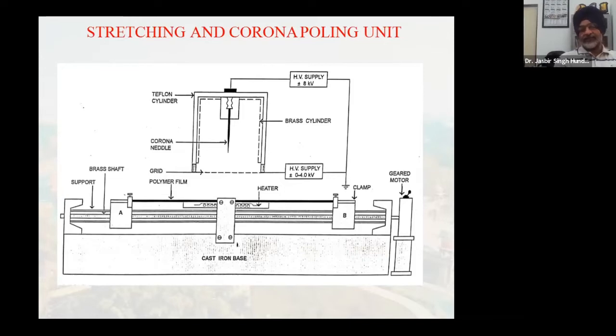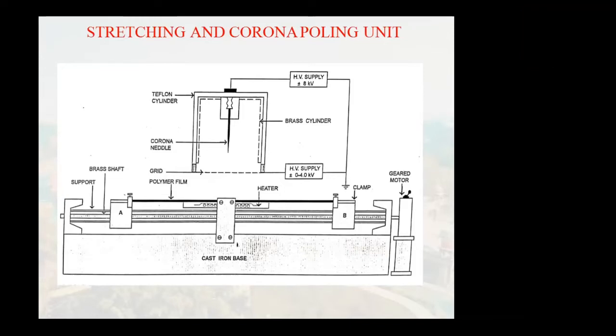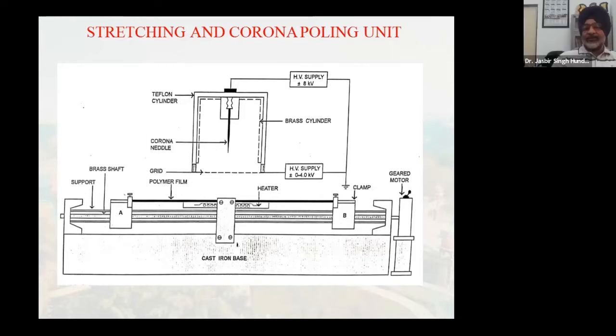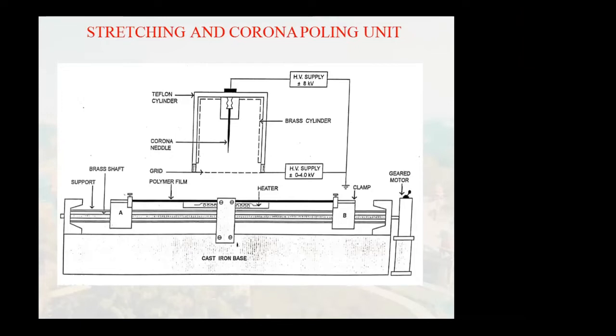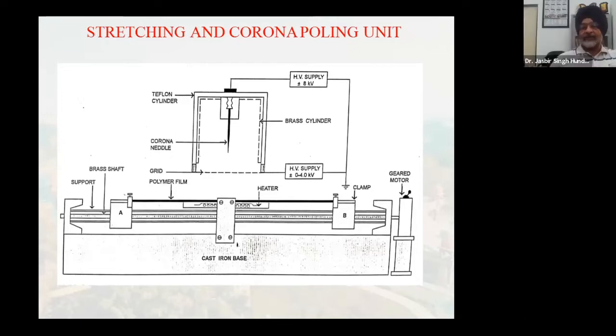And sometimes in some of the polymers, simultaneously stretching and corona poling is done. That means the film is stretched at the same time the field is also applied, right? What happens with that is that when you stretch the film, the dipoles are already moving because of stretching, because of physical movement of the film. And at the same time the field is applied, then that may also increase the polarization.